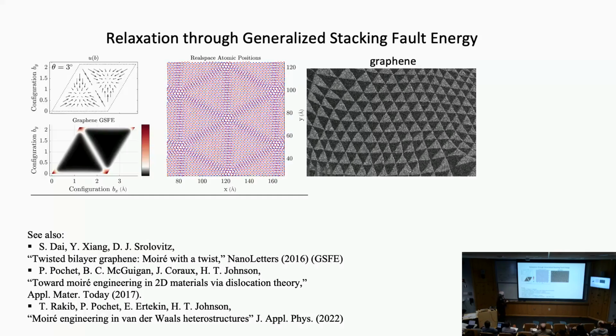So here is a color-coded version of the energy landscape that I mentioned. Namely, you take one layer and you translate it with respect to the other layer by a single atomic unit cell, and you produce the energy landscape. Black is low energy, red is high energy, white is intermediate. From the energy landscape, you can calculate gradients, which can be translated into the forces, the displacements of the atoms. And with this, you can produce this picture, which includes the full atomic relaxation that gives you the lowest energy configuration. And here, you can easily see these triangular regions, which correspond to what is seen experimentally.